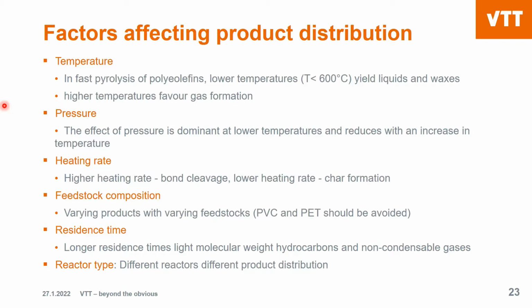If you have a higher heating rate, then you are basically breaking the bonds of the polymer, so you have bond cleavage. But if you have a lower heating rate, which means slow pyrolysis, then you basically tend to form char. So there is the secondary product, char, from the plastics.